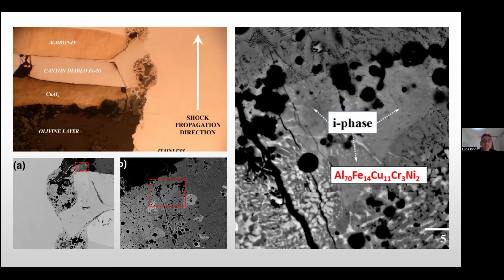And the results are pretty exciting. Look at this. Look at the degree of structural perfection. Look at all the reflections following the perfect five-fold symmetry, which is really great. So it seems impossible that such a perfect quasi-crystal can be produced in nanoseconds in a collision, in a very heterogeneous collision with several phases involved. So it was actually a surprise.